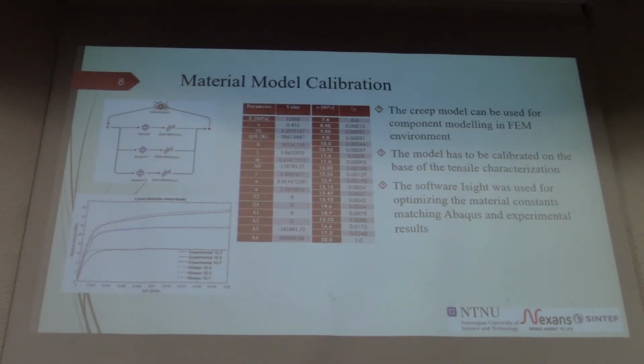An example of the calibration that can be done is using Abaqus and modeling the specimens and the test in Abaqus, and then matching the data extracted from the finite element simulation with the experimental data, and then running an optimization loop that will find the array of constants starting from intervals that have to be set by the operator. They have to be intervals that make physical sense, for example, for the activation energy.